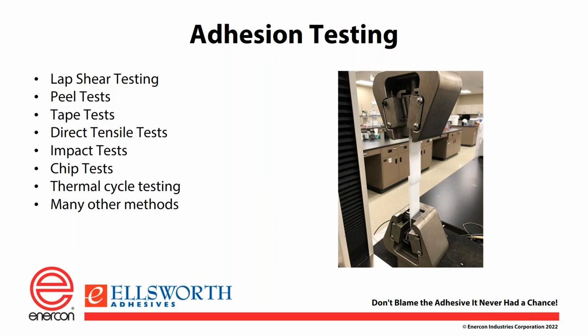If you want to try to predict how your adhesive will perform, you can do some adhesion testing. Typical adhesive tests are lap shear testing, and that's what's pictured to the right. That is a lap shear test where two parts are bonded together with a 1/2 inch overlap and then pulled apart by a universal tester, and you can get a force in pounds per square inch. You can choose the substrate base to match it to your assembly and predict both the strength of the bond and the typical mode of failure. Other tests exist, and even more beyond what's on this list.